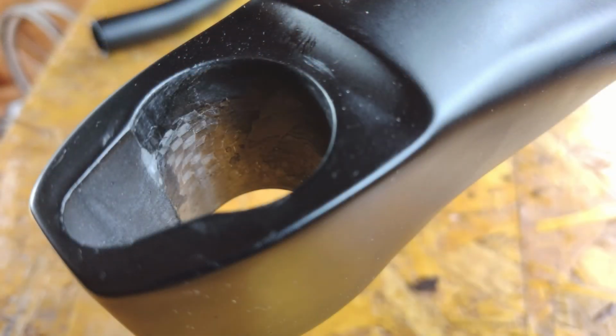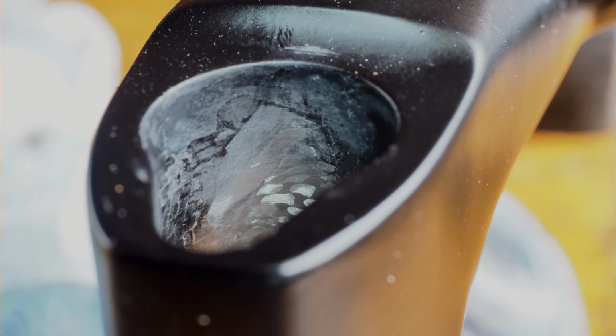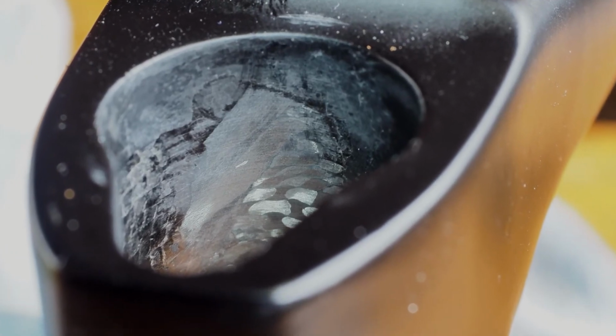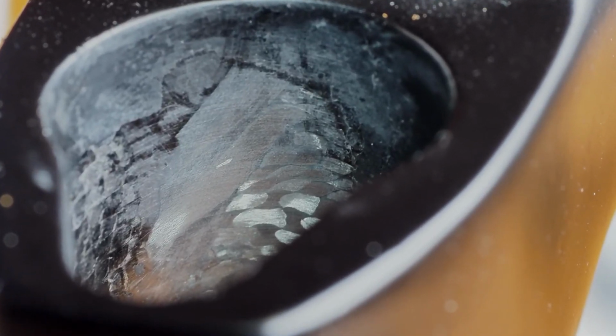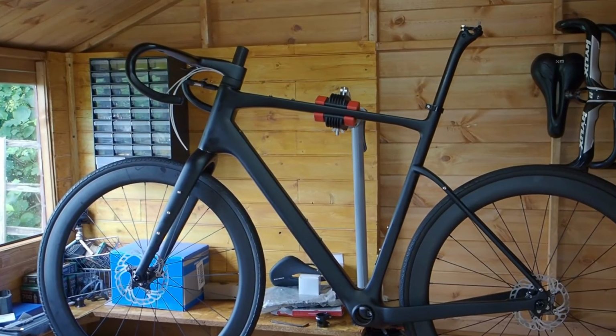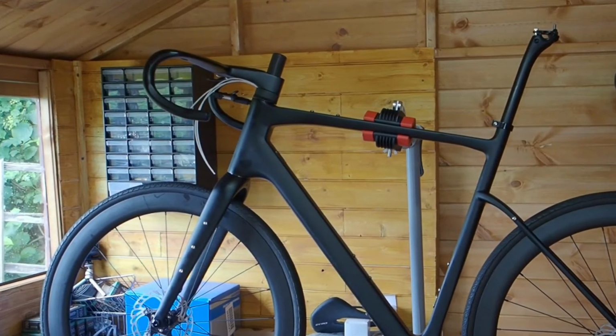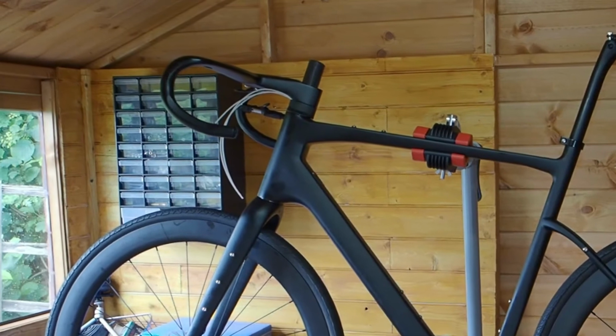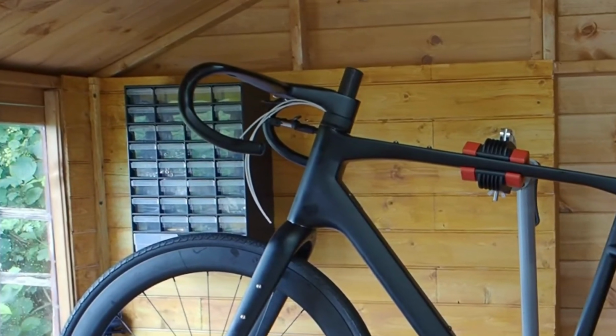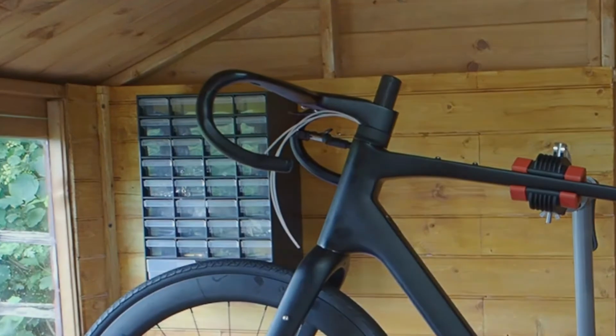The only area of bare carbon I can access is in the steerer tube hole. This has regions of woven cloth and unidirectional fibres. It looks to me as though it was moulded to near net size and then reamed out after moulding. I can't see any moulding defects, cracks or delamination, so it all looks fairly well consolidated. Because I've only been able to carry out a limited quality assessment, like the forks, prior to using them, I'll give them a high load test while listening for unusual noises, and then afterwards re-inspect the unit.